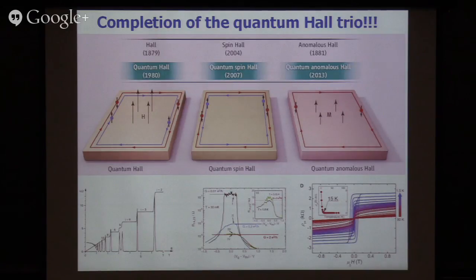So this time, unlike in the case of the quantum spin Hall effect, which was predicted in 2006 and already seen in 2007 experimentally at the University of Würzburg, it took a little bit of time. The material was predicted in 2010 in a Science paper, but then only last year, a group out of Tsinghua University first saw the quantum anomalous Hall effect in chromium-doped topological insulator.